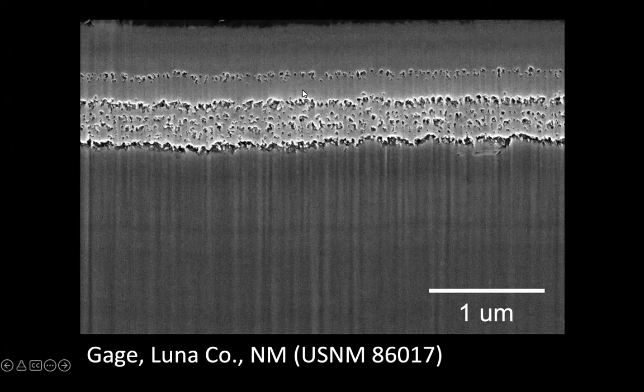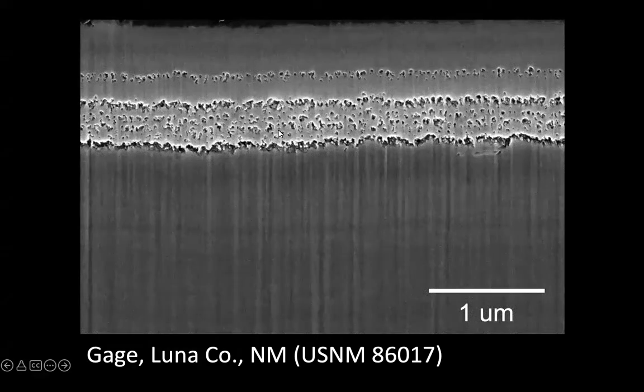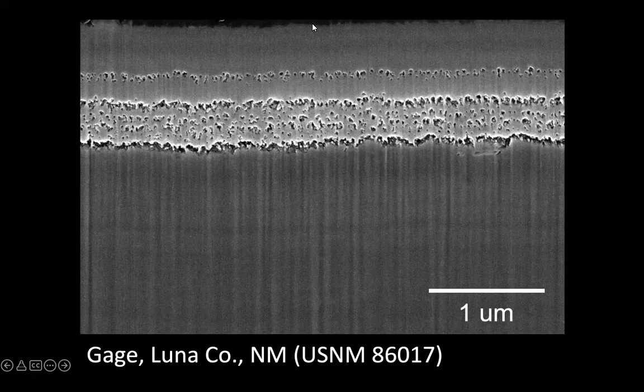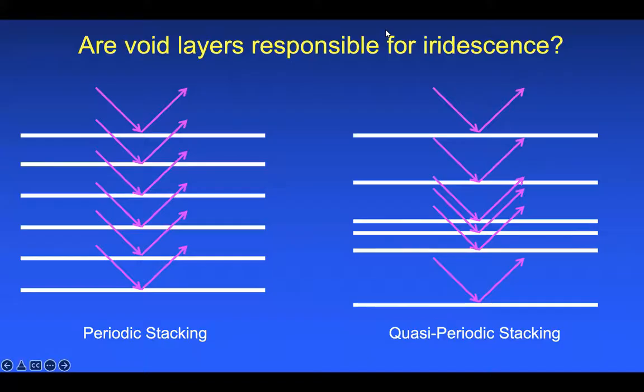But what we always observed in all of our colored specimens was that there were layers of vacancies underneath the surface and fairly close to the surface of the specimen. But what was interesting was that these vacancies are not strictly periodic in the way that they are arranged. They're kind of quasi-periodic. Now, that actually made sense to me, because if you have a strictly periodic stacking sequence, then you get a very strong angular dependence. Just like opal, you change the angle of opal relative to your eye and different colors flash out.